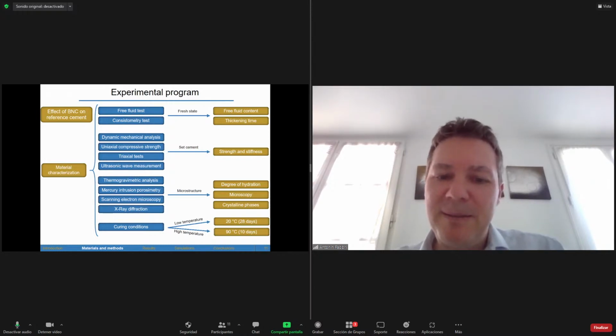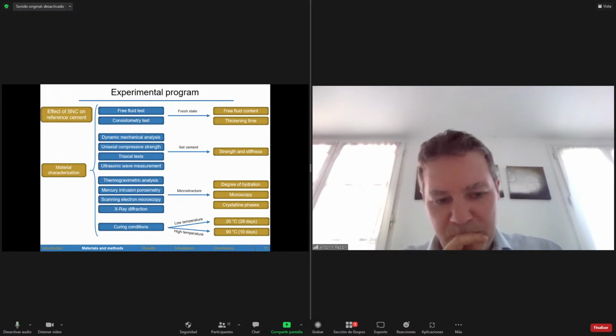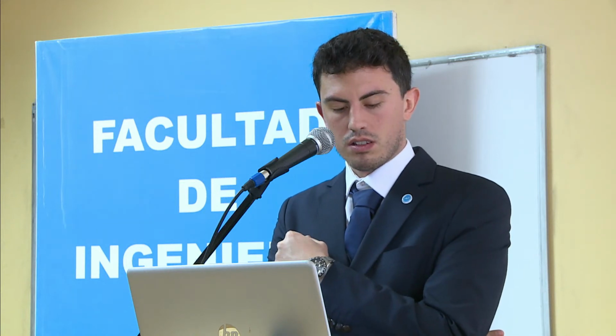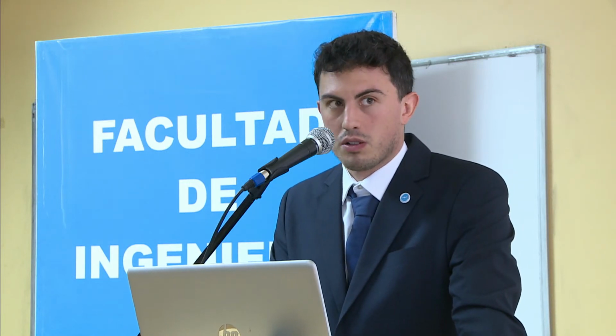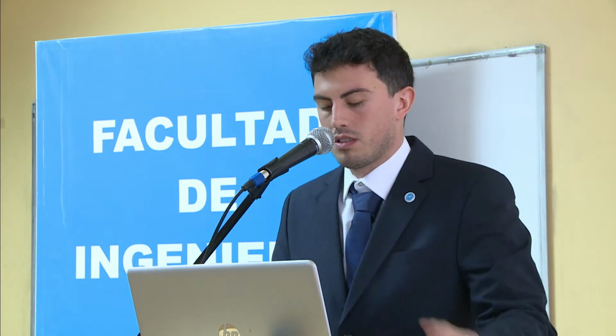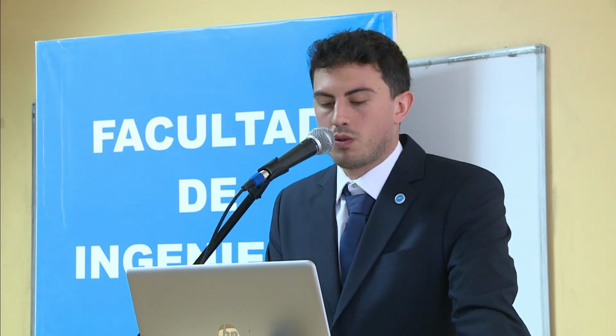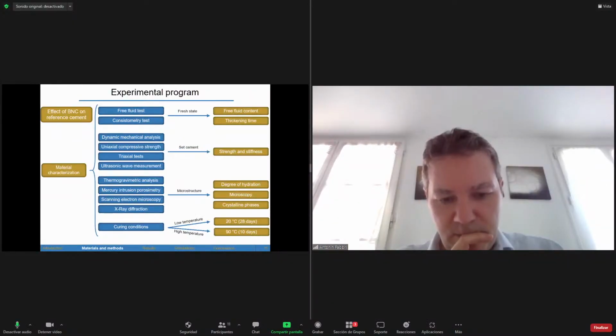Yes, actually we tried to do that, but we didn't have enough information on the triaxial test. It was quite a challenge to prepare the triaxial test, and a lot of samples were broken before testing them. While testing, it was quite difficult to obtain the value of the deviatoric stress in order to determine the phi parameter and C.